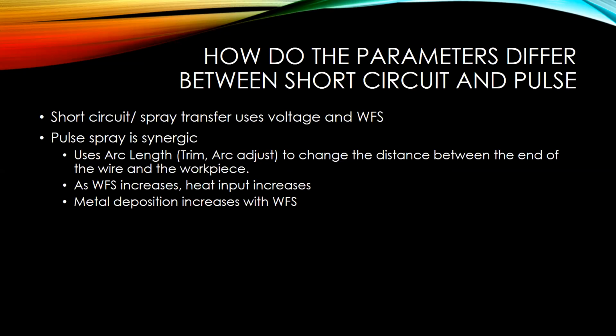As your wire feed speed increases, your heat input increases. So it's synergic. Once you set your arc length, that distance between the end of your wire and the puddle, the machine is going to be synergic with your wire feed speed. So as you adjust your wire feed speed, it's going to maintain that same distance, no matter where the wire feed speed is. But as you increase your wire feed speed, your metal deposition will also increase.